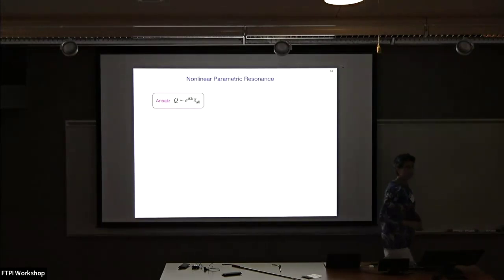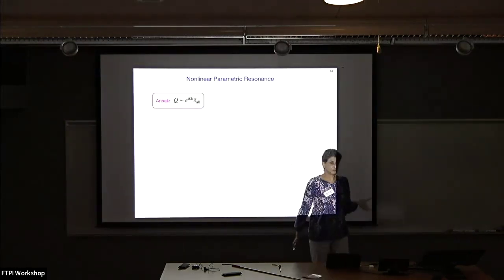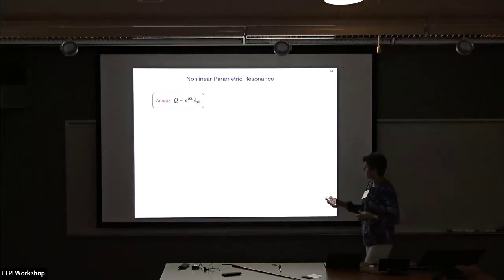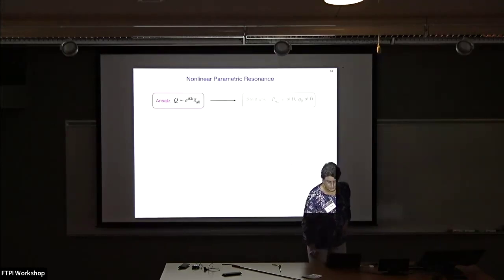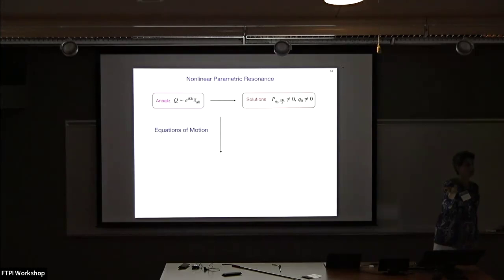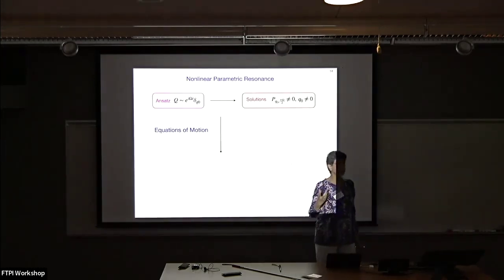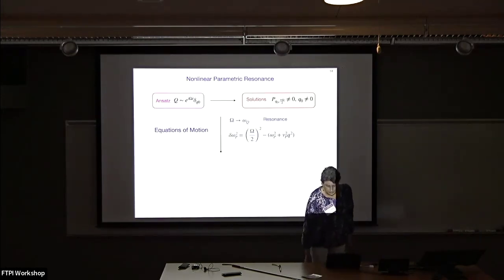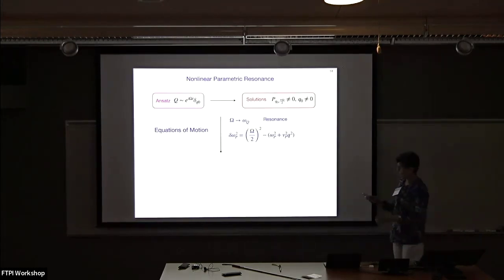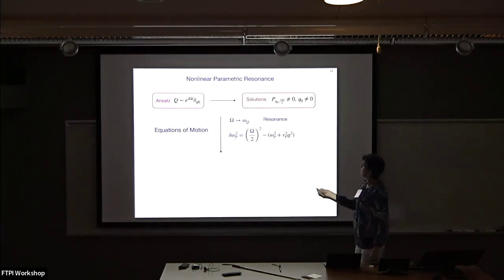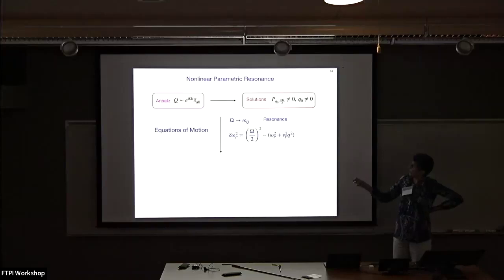Now, inspired by these beautiful numerics, we decided to see whether we could understand the system using just three dominant modes that the numerics told us. So what we do is we take an ansatz where we're on resonance, and we're going to look for solutions of the form Q0 and plus or minus omega over 2, omega being the drive frequency, where Q0 is not 0. We look at the equations of motion, again at resonance, and we define this detuning expression, where you notice that if this were 0, then we would be at resonance. This is the dispersion, and this is the resonant frequency of the self-harmonic. And what we're asking is, if we look for these solutions, do they enforce this resonance?